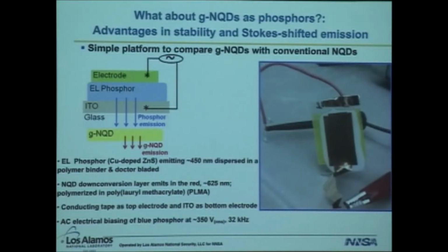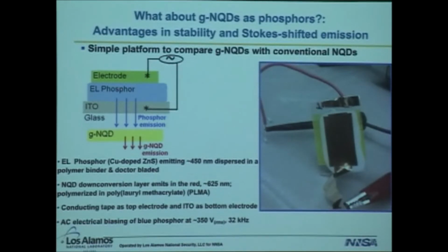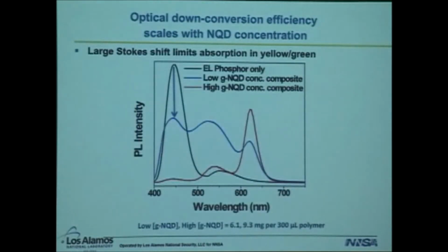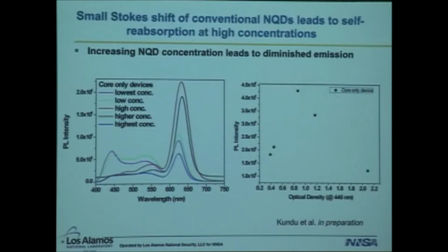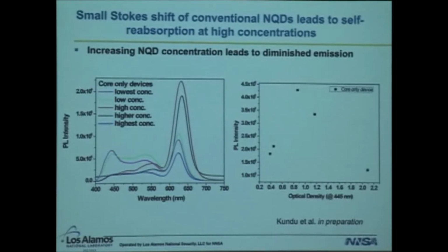So we've also demonstrated that giant quantum dots can be used as phosphors, and here we're taking advantage of stability and Stokes shifted emission. I think I'll skip this. Yeah, and so this is a demonstration of why a bigger Stokes shift is better. And so here are data of PL intensity versus optical density, where optical density can be viewed as correlating with the concentration of quantum dots in your system. So in this case, we're using quantum dots as phosphors.